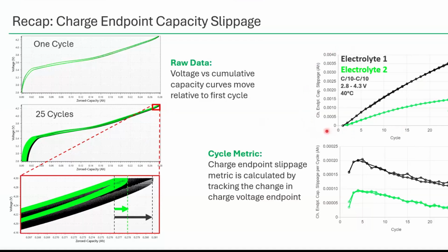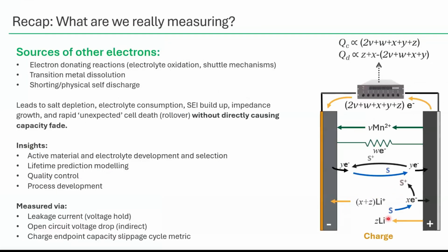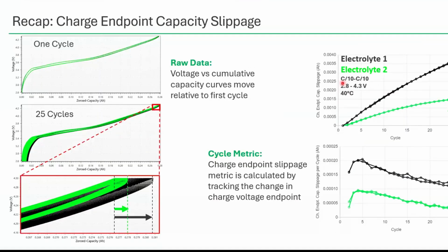With very high accuracy and precision cell testing equipment, this is a very consistent cycle metric. These are pair cells made on our pilot line with 2 different electrolytes. Electrolyte 1 just has vinylene carbonate. Electrolyte 2 has vinylene carbonate and propane sultone, which really starts to shut down these high voltage reactions at the cathode and mitigate this charge endpoint capacity slippage. What's likely happening is we've got a lot of electrolyte oxidation, counting a lot of excess electrons, which drive our endpoint to higher and higher capacities.